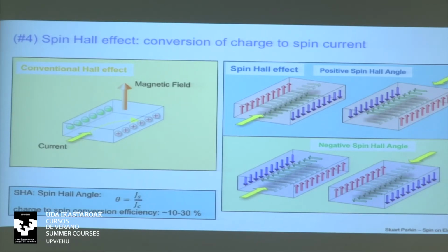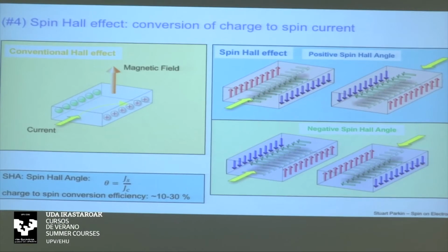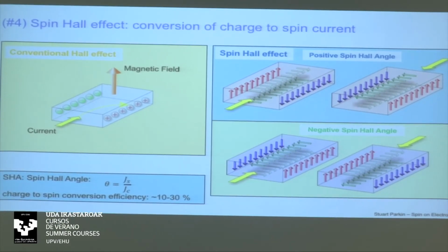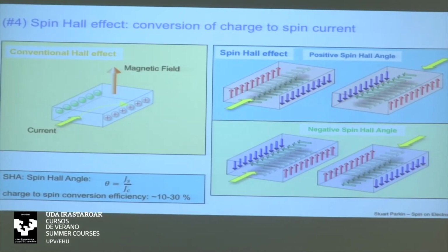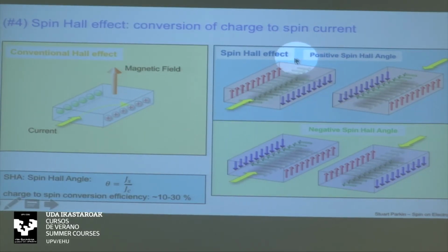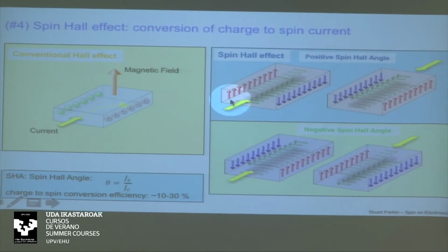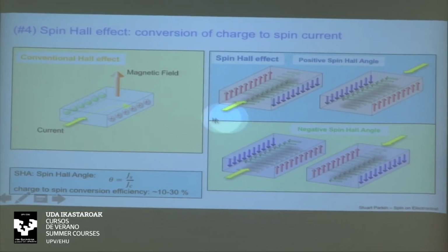And so this has already been discussed extensively in several lectures, including Claudia's lecture. Just to remind you, if we take a system, typically with strong spin-orbit coupling, then in conventional metals, you pass a current, shown here as yellow, and you derive a spin current which flows perpendicular to the surfaces of this wire, where the polarization of the spin current is along the circumference of this wire.